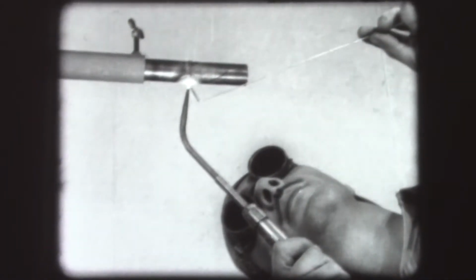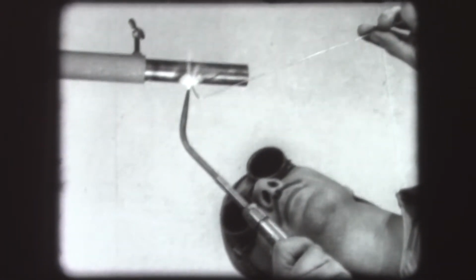In this type of weld, the most difficult point is the underside of the tubing, because the metal tends to fall away from the weld if the applied heat is too great. Heat carefully and don't permit the metal to become thin. When the weld is stopped for any reason, start again by making the metal thoroughly molten. Then add the rod and advance the puddle. Stop the weld when the top of the tubing is reached.